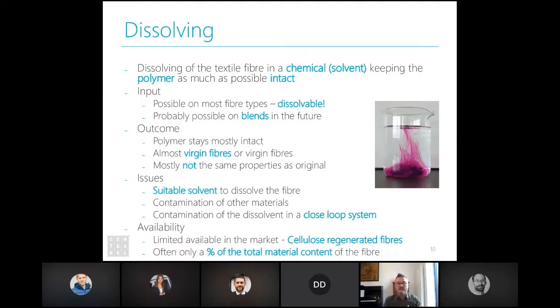Issues are to find a suitable solvent to dissolve the fiber, contamination of other materials, and contamination also of the solvent in a closed loop system. So there are sometimes washing residues or dye stuff that might pollute your solvent, and you want to try to reuse your solvent, so you don't want these products in your solvent. They are limited available in the market, and in most cases are cellulosic regenerated fibers. Also, it is only a certain percentage of the fiber that is recycled.